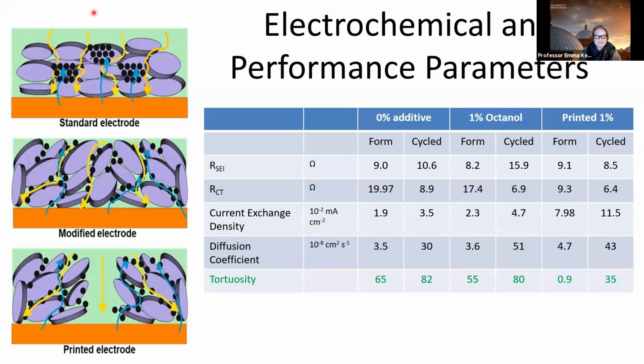So here we just summarize that electrode. We can modify the tortuosity and the properties by changing the additives that go into the electrode, and also by changing the structures of the electrode to optimize transport properties of electrons and ions. And the big thing to notice here is just our tortuosity is very low in the printed electrodes because we've got some gaps that our electrolyte can go through to be able to then get to the electrodes.